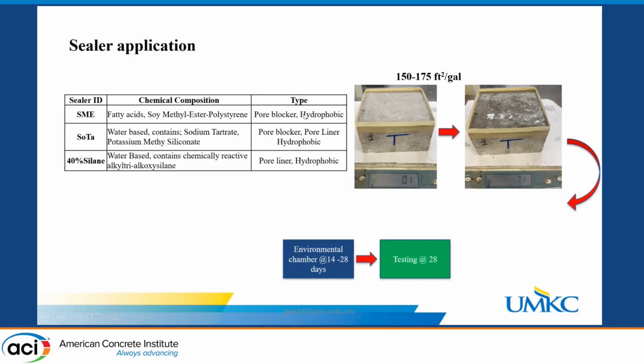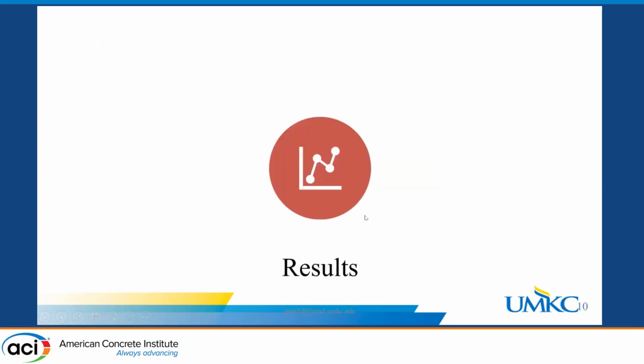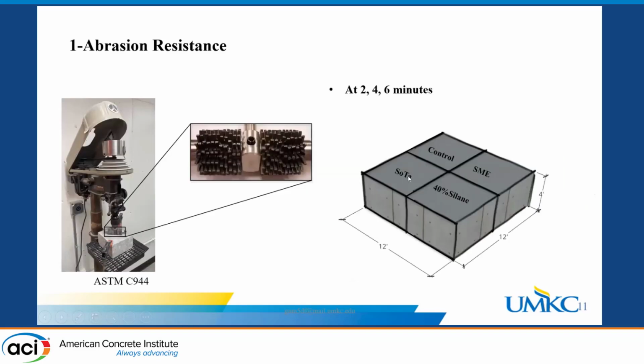Based on the specifications of all of the materials, we back calculated and applied all of the sealers at 150 to 175 square feet per gallon. After we applied the sealers, we returned all the material to the environmental chamber and tested all of the specimens after 28 days. Let's look at some results from our experiments.